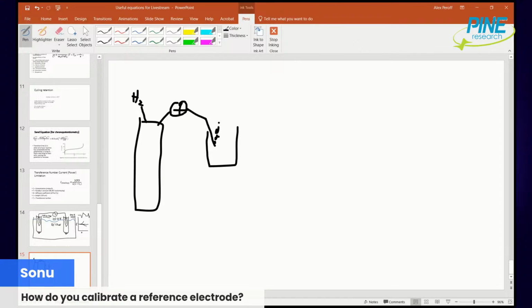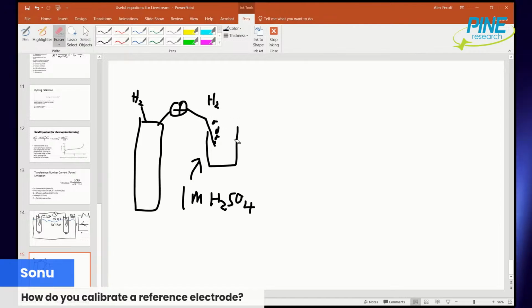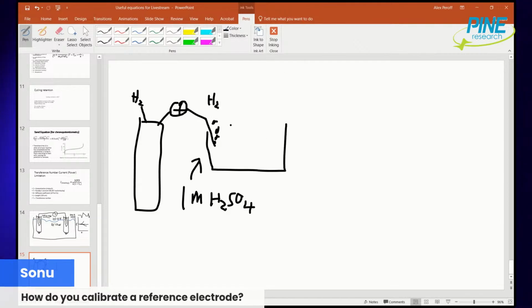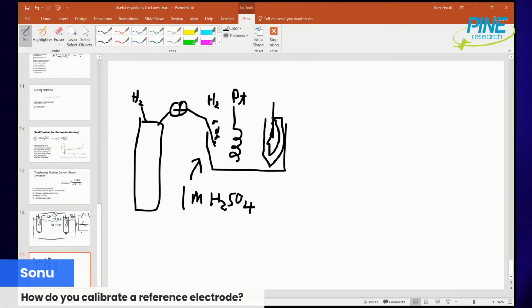So I have hydrogen, H2 gas, in 1 molar sulfuric acid. And then I would have a platinum wire in my solution. Actually, I would just take a counter electrode, a platinum wire. And then I would relatively quickly put in my reference electrode. Maybe it was silver chloride. So I'd put my silver chloride reference electrode in here, Ag/AgCl.